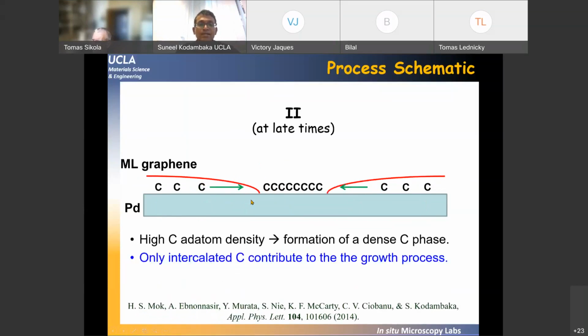But once you have more graphene-covered surface, we think that a dense phase of disordered carbon forms on the surface that prevents, or very much limits, the attachment of these carbon atoms to the existing graphene islands. And at later times, it's the intercalated carbon that contributes to the growth of the graphene islands.